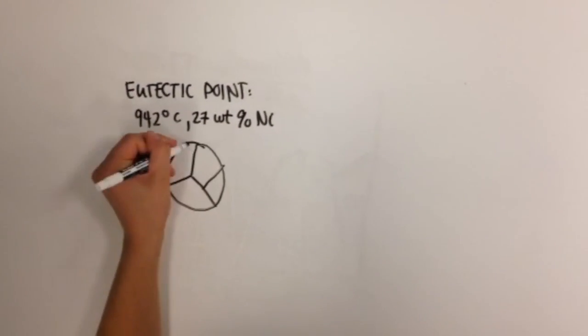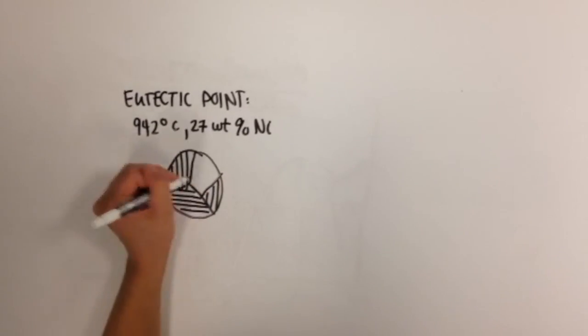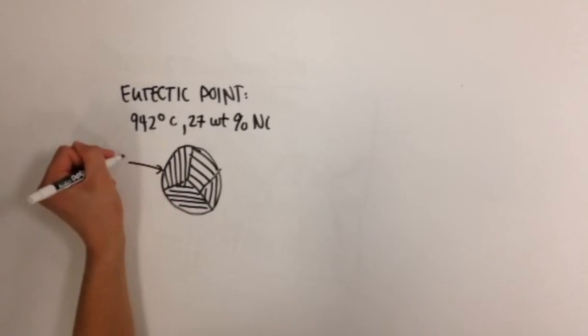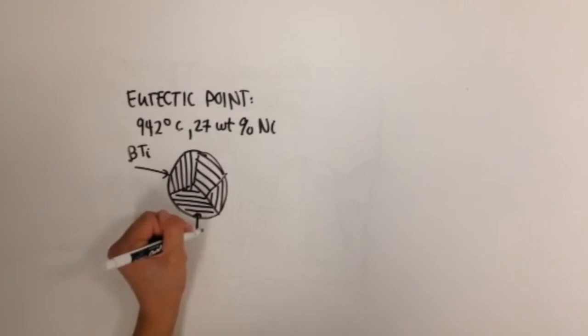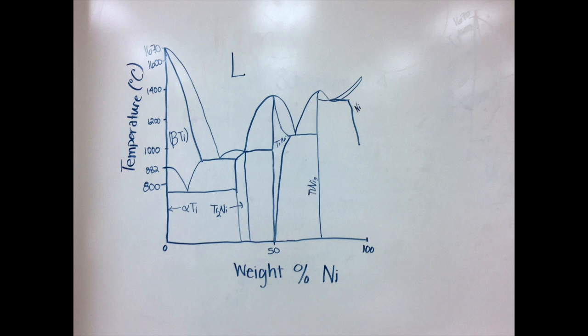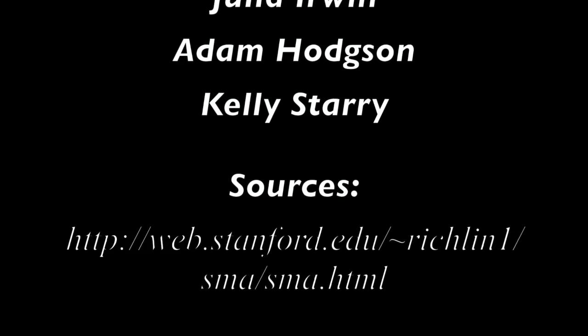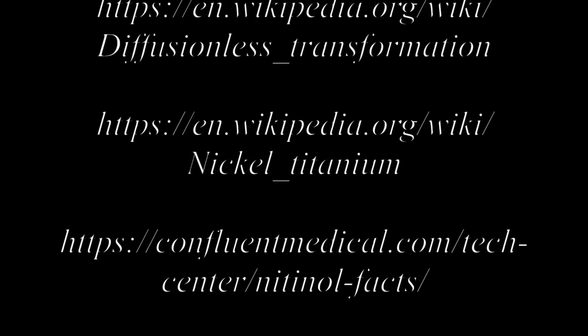alternating stripe patterns. There is also a peritectic point at a temperature of 765 degrees Celsius and 6 weight% nickel, which involves a transformation from beta Ti to alpha Ti and Ti2Ni. Additionally, there are 2 congruent transformations, one at 1,310 degrees and 55 weight% nickel, and the other at 1,380 degrees and 77 weight% nickel. These transformations involve no change in composition.